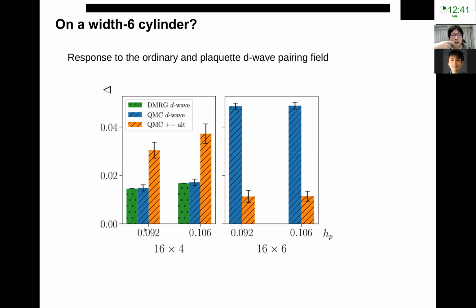We apply two kinds of pairing field: one tries to enhance the ordinary D-wave, and the other tries to enhance the plaquette D-wave. We found that at width 4 cylinder, the response from the plaquette D-wave is larger than the ordinary D-wave - this orange band is for plaquette D-wave, this blue bar is for ordinary D-wave. However, if we consider width 6 cylinder, the ordinary D-wave response is much stronger than the plaquette D-wave. So this is not surprising - this kind of pairing symmetry is special to the width 4 cylinder.